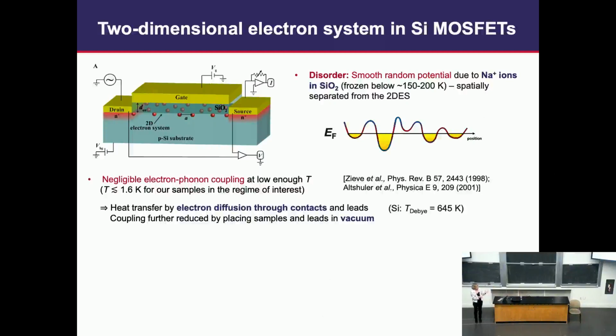This is a well-known fact in silicon: at low enough temperatures, the electron-phonon coupling is negligible. This is what we need for MBL. So this is an ideal system, and the heat transfer from the 2D layer is really through these contacts, labeled source and drain, and up the leads in your cryostat, the wires. And if you put all this in vacuum, you reduce the coupling to the rest of the world even further. So this is what we did, unless I tell you otherwise.